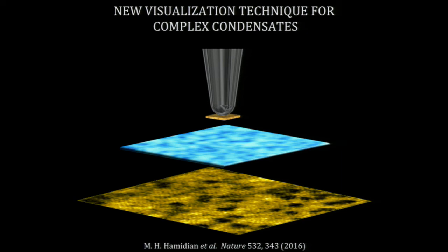Does it make a difference if you rotate the sample for it? That's an excellent question. We never got to the rotation, but what I will point out is that we know that it's not rotated. Because if you have one crystal structure rotated relative to the other and you were to scan, you would have a moire pattern, essentially an interference pattern between the two. And we don't get that. So once again, Mother Nature has been very kind: once we pick it up, it nicely registers itself to the lattice. It rotates itself exactly back into the lattice. But you're right, it would be an excellent experiment to see how the IC signal would change as you rotated the sample.